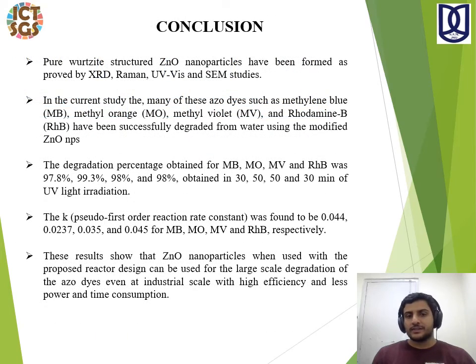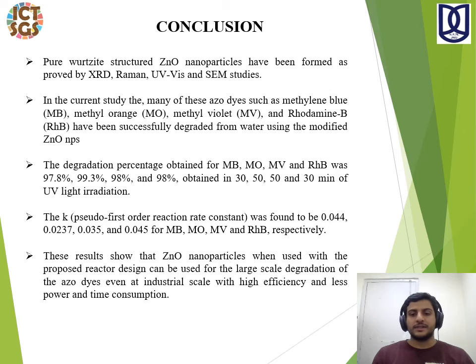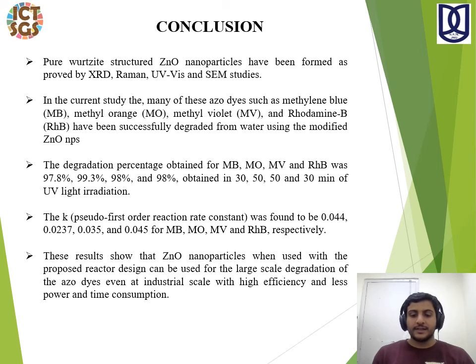In conclusion, we synthesized pure zinc oxide nanoparticles and characterized them using XRD, Raman, UV-visible, and SEM studies. We successfully degraded four different dyes using nanoparticles alone, obtaining degradation percentages of 98, 99, 98, and 98% in 30, 50, 50, and 30 minutes respectively. The pseudo-first-order reaction constants are also very good. These results show that these nanoparticles can be used in the proposed reactor design for large scale degradation and can also be scaled up for industrial purposes with high efficiency.